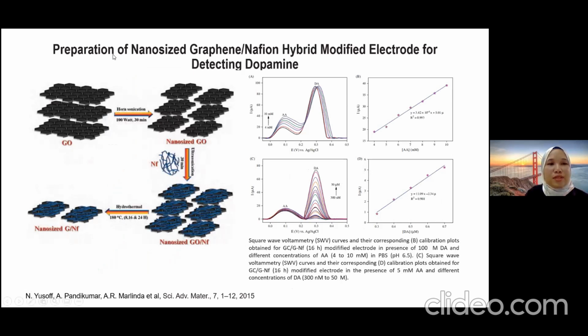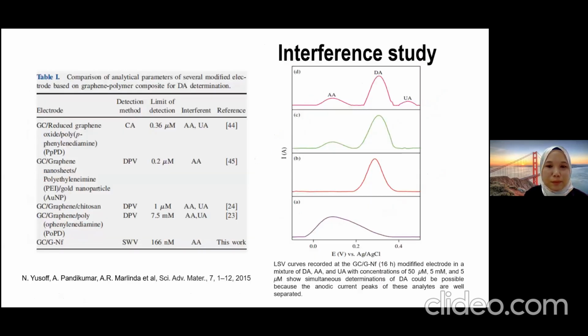Okay, this is another one, the preparation of nanosize Graphene-Nafion for detecting dopamine. Just now I showed the same modification method to detect nitric oxide, but this one can also be used for detecting dopamine. So square wave voltammetry here shows that the hybridization of Graphene-Nafion can be used to detect dopamine concentration from 300 nanomolar up to 50 micromolar. So we can see that from the calibration plot, we can calculate the limit of detection. The limit of detection for that SWV technique is 166 nanomolar.